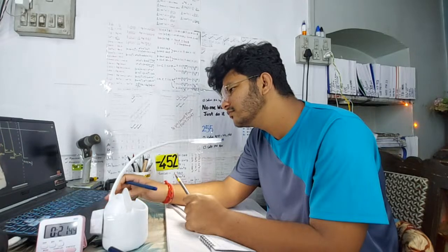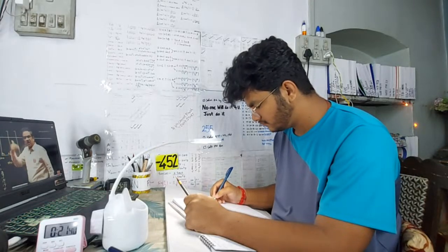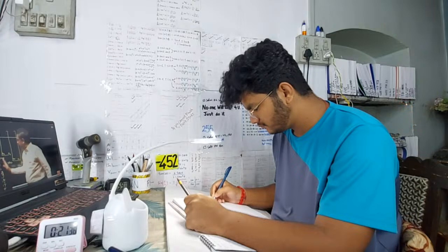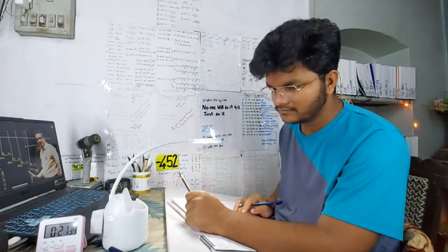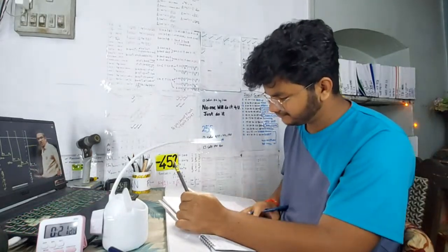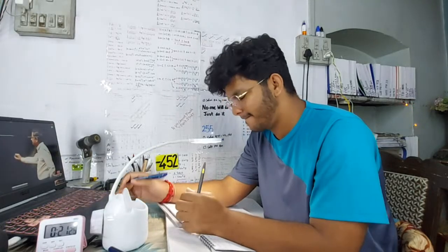Martensite formation starting temperature. At different temperature ranges, the austenite transformation product will be different. Up to 550 degrees centigrade, austenite will transform into pearlite. Below 550 degrees centigrade, by constant temperature holding, austenite will transform into bainite. Below 210 degrees centigrade, austenite will start transforming into martensite. These are the observations. Let me try to show you that.